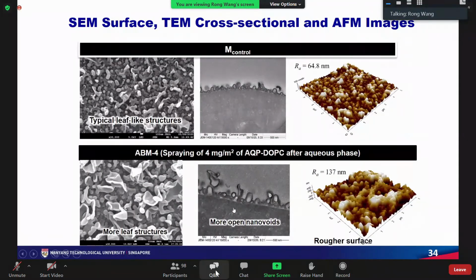Now, I'd like to show you the SEM, TEM, and AFM images of our two membranes. One is the control without aquaporin incorporation. Another is the aquaporin-based SWRO membrane. With the incorporation of the aquaporin, the polyamide layer has more leaves. It also has more open nano voids compared to the control. The surface roughness was much higher as compared to the control membranes.